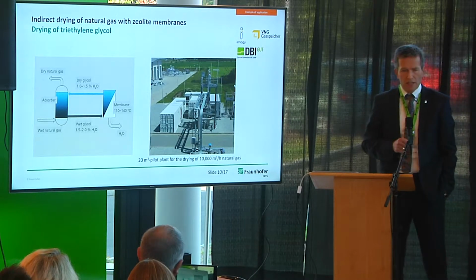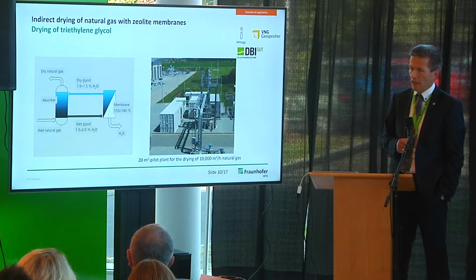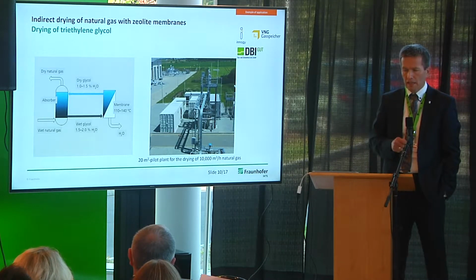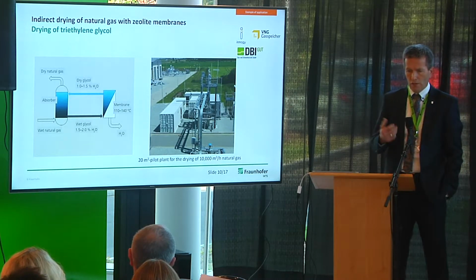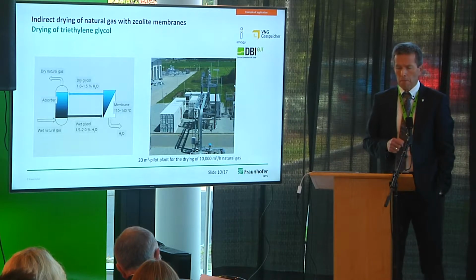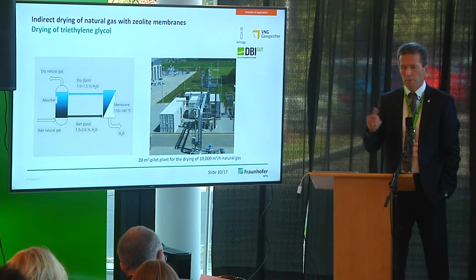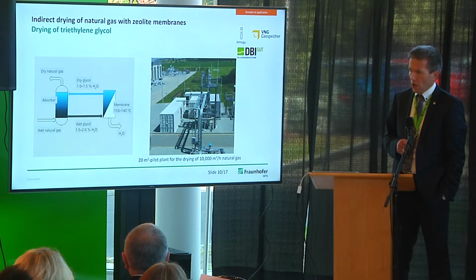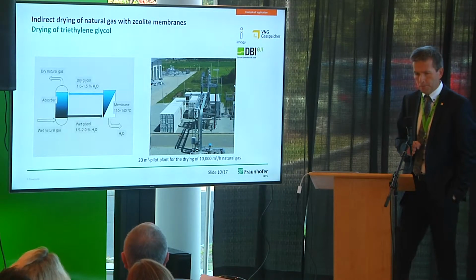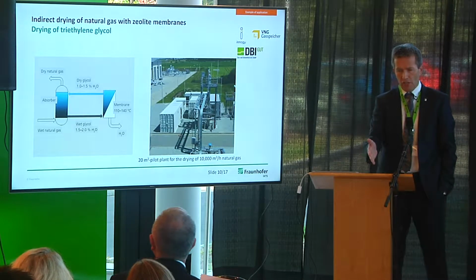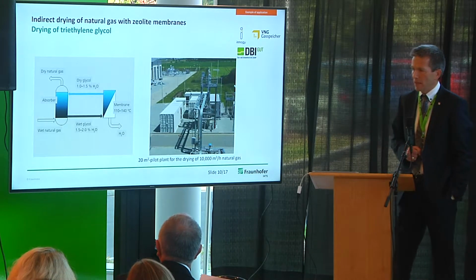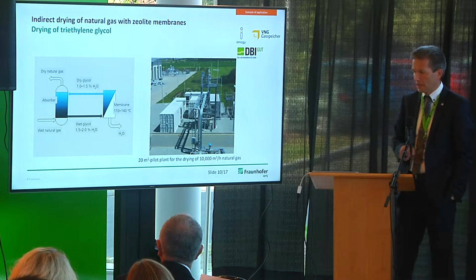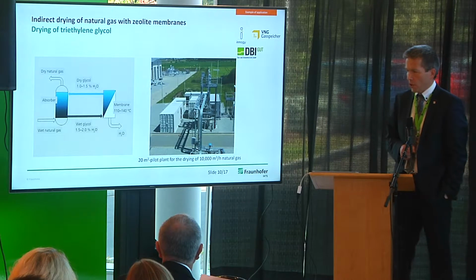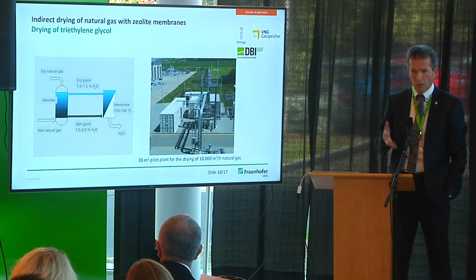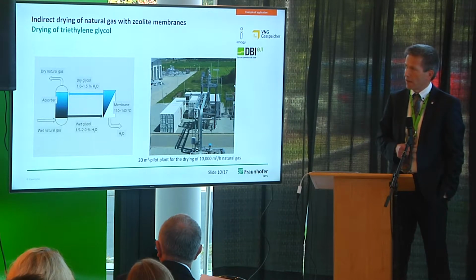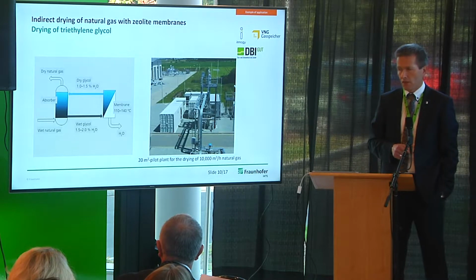And this membrane was tested for the dehydration of tri-ethylene glycol, first in our lab. Tri-ethylene glycol is an absorbent for the drying of natural gas and is normally dehydrated by a distillation above 200 degrees C. And this high-temperature distillation can be replaced by the application of our zeolite membrane. And again, after demonstration of the feasibility in our lab, we implemented 20 square meters of these membranes in the pilot plant, which is able to treat 10,000 cubic meters of natural gas. And this is running now for 1.5 years. And again, here we hope that Energy and VNG decide to build a large-scale plant in the near future.